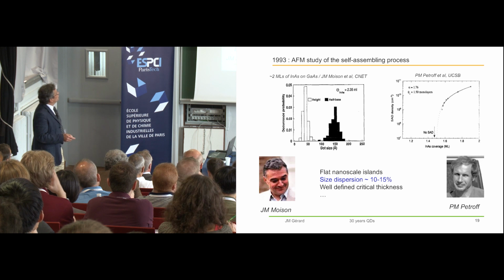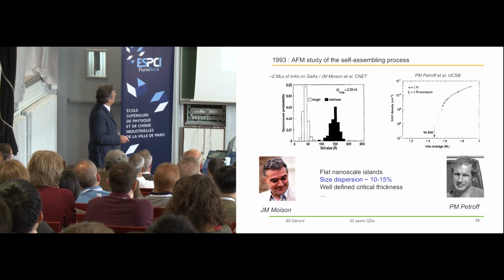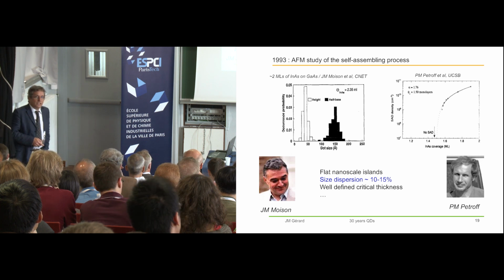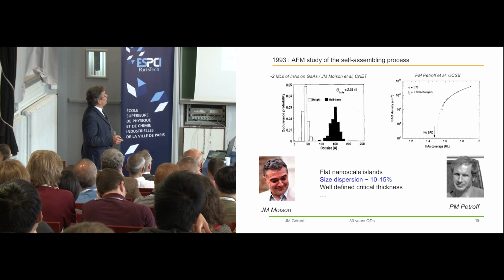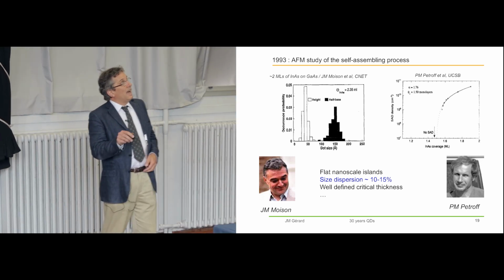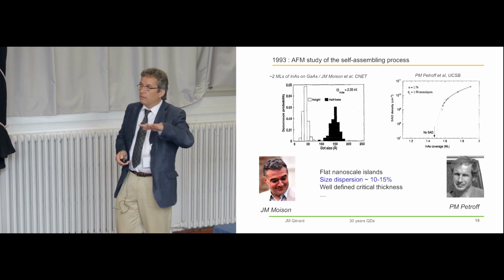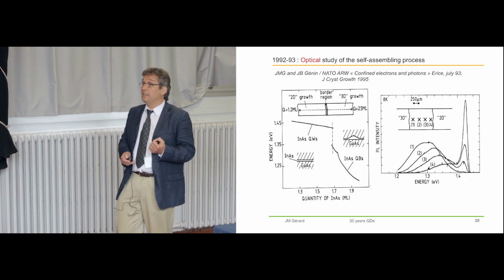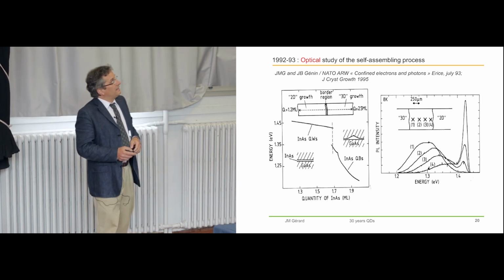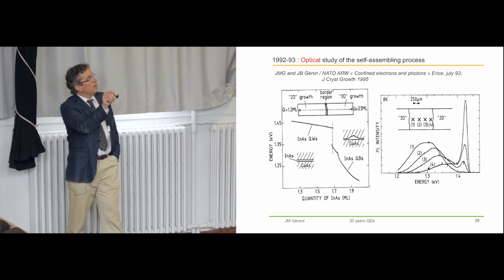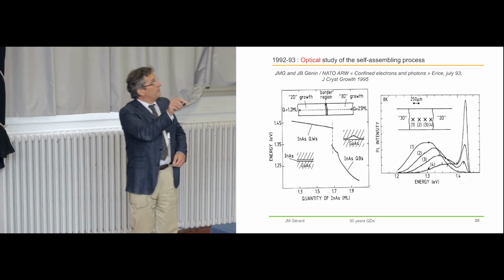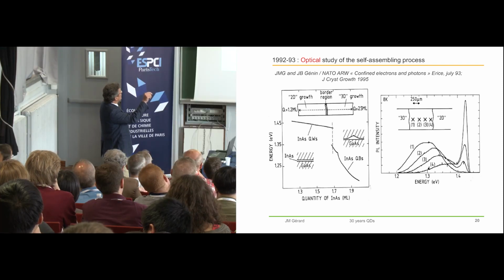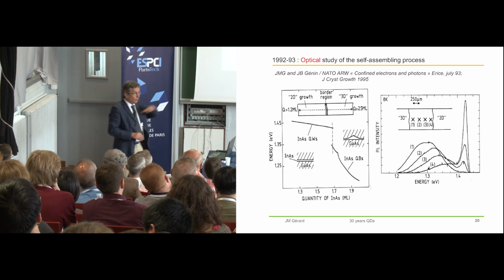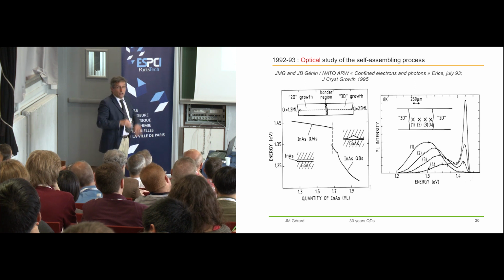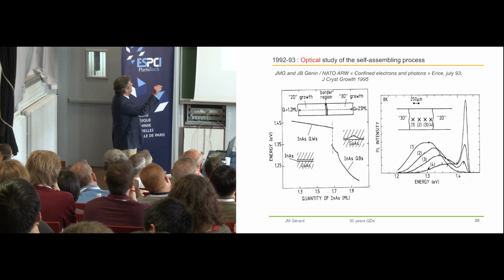AFM is nice, but I would like to show you also that optical studies can give you very nice, very detailed information about the formation of the quantum dots. The questions we had at that time were the following. How do we go from a two-dimensional layer to a three-dimensional layer? What happens in between at the transition? For that, you can grow a sample for which the quantity of indium arsenide decreases or increases from below the critical thickness to above the critical thickness. So you have a region where indium arsenide forms a quantum well, a region where the indium arsenide forms an array of quantum dots, and so what happens here in between?